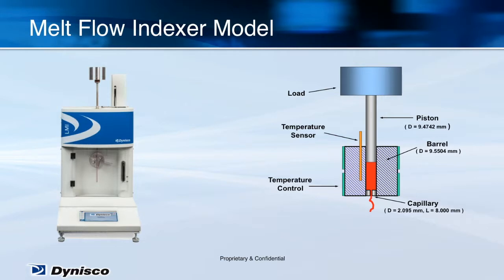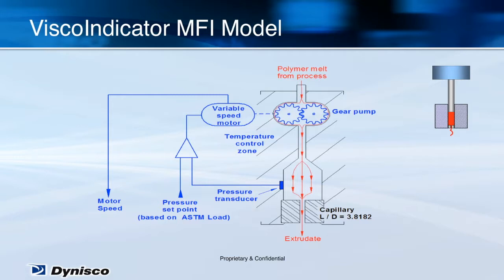Because of the short capillary L over D, this rheometer measures not only viscous losses in the capillary, but also viscoelastic losses in the capillary entrance. This means that the measurement is a function of both the rheometer geometry as well as the polymer viscosity. In other words, the ASTM D1238 standard defines both the apparatus and the polymer test conditions. Melt flow indexers must be hand-loaded with pellets and weights to create shear conditions, so the test requires a technician and it has to be done offline.